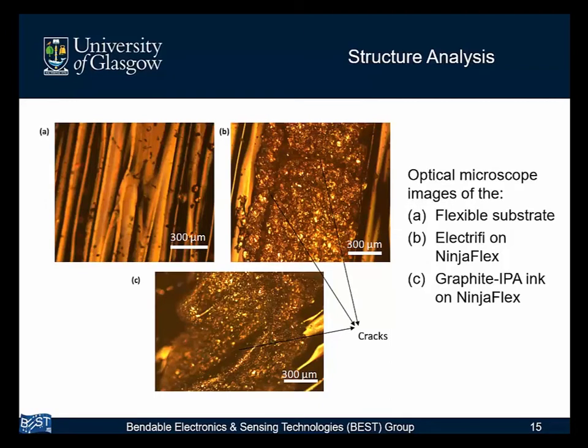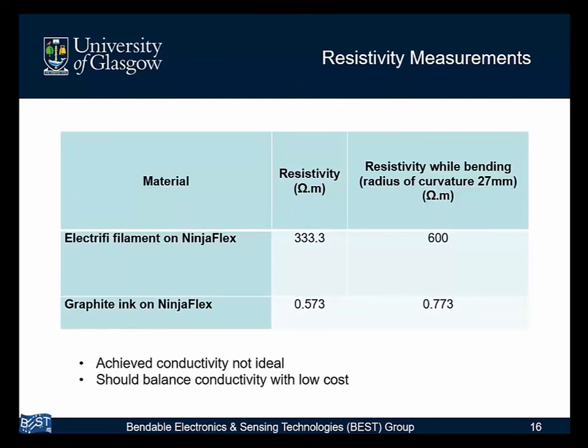And as you can see, it's clear to see for any material people around here that there are some cracks in the system itself. A lot of this can happen either through printing or through the bending as well. And this is one thing, moving forward, to try and avoid and optimize. And like I said, in terms of binders for the ink, this can hopefully be taken forward. And in terms of tweaking the printing mechanism for FDM printers, the cracks for the electrifi filament can also be solved.